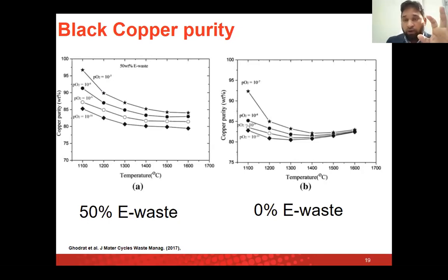Look, overall, when we have highly reducing conditions, under those conditions, the copper purity will increase, of course. But at the same time, we will also lose copper in fumes. That's why we use conditions like 10 raised to power -7 partial pressure rather than 10 raised to power -10 or 11 or 12. And also to achieve those higher conditions is really challenging. And Winnie knows about that, because when she was doing her magnesium separation experiments, I know it's not easy, isn't it? Yeah. So that's not easy to achieve anyway.